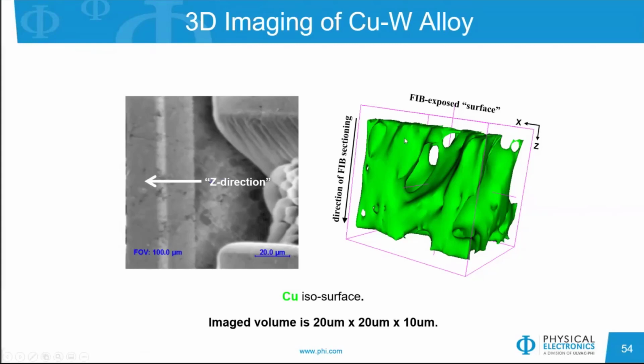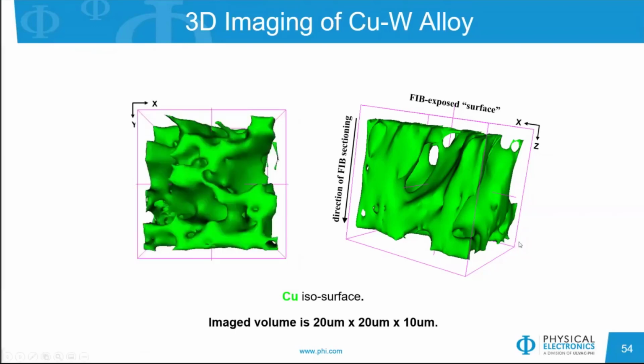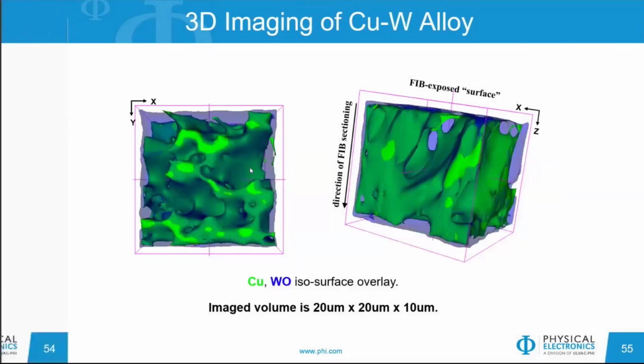And you can see the reconstructed 3D image depth profile of the distribution of copper in the sample here, and just see the various grain orientations of it and the non-uniformity of it and how it's preserved, and looking at a different top-down version of it so you can see how the grains are in this alloy, as well as looking at all the different other materials. So this was a copper tungsten one, so looking at the copper tungsten distribution,